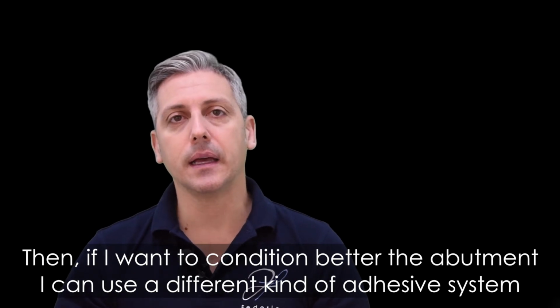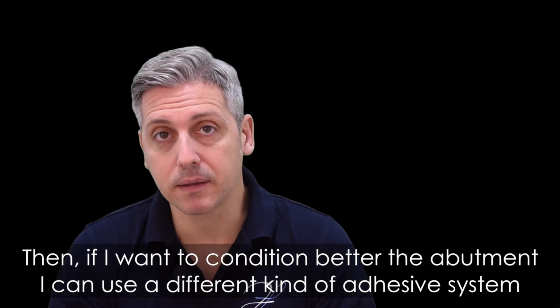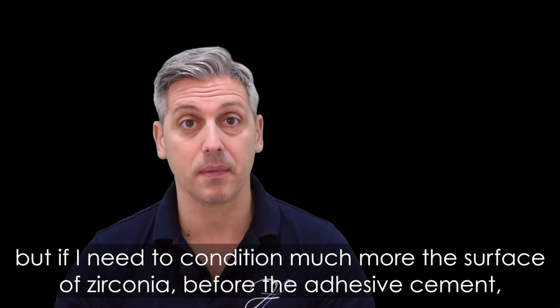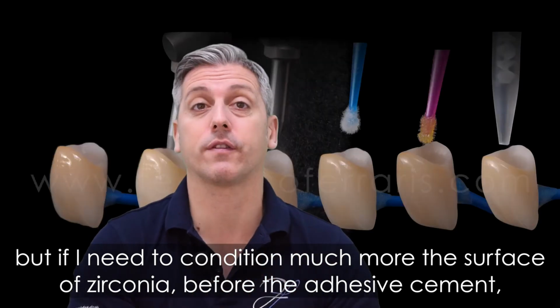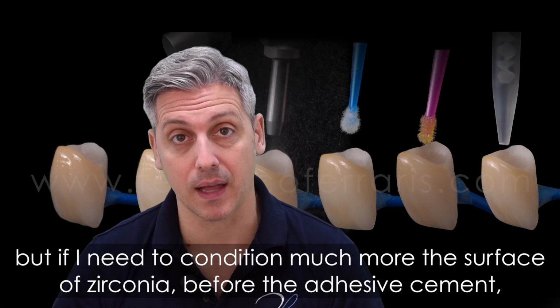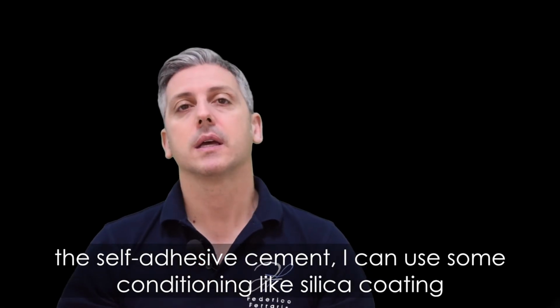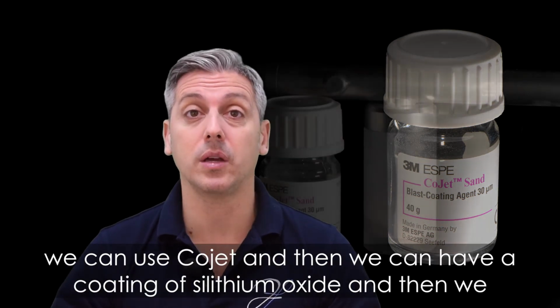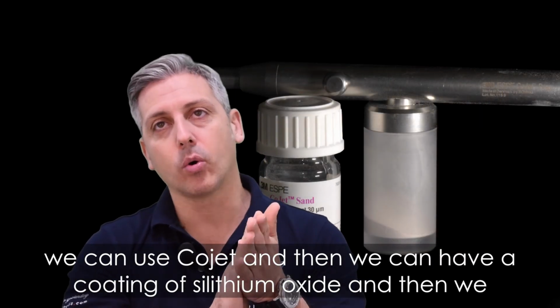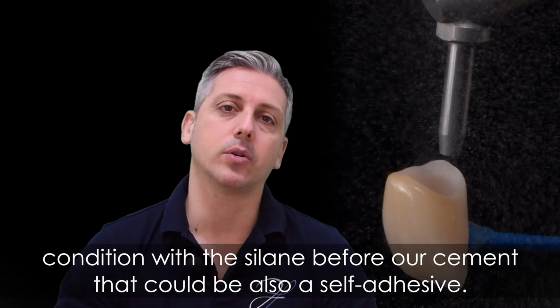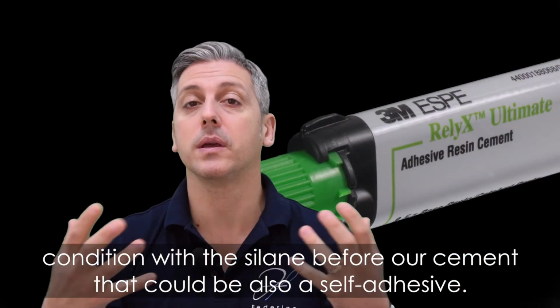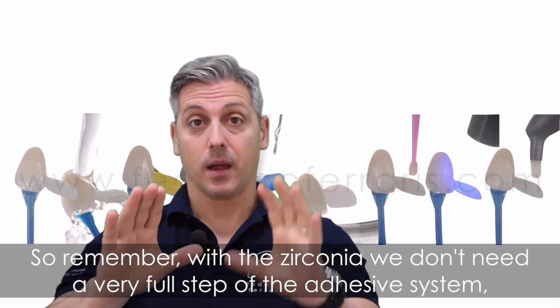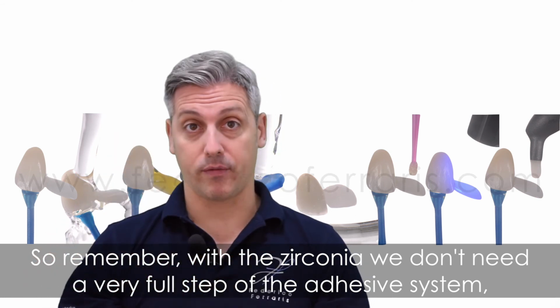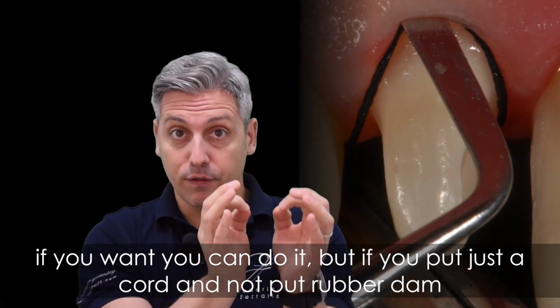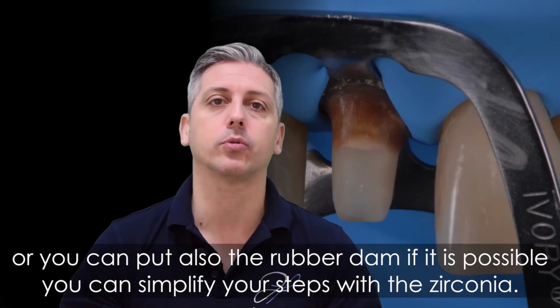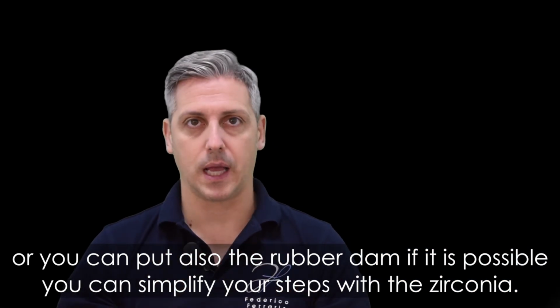Then, if I want to condition the abutment better, I can use a different kind of adhesive system. But if I need to condition the surface of zirconia much more before the self-adhesive cement, I can use some conditioning like silica coating. We can use CoJet, and then we have a coating of silicon oxide, and then we condition it with silane before our cement, which could also be a self-adhesive. So remember, with zirconia we don't need the very full steps of this system. If you want, you can do it. But if you just put a cord and not a rubber dam, or you can also put the rubber dam if it's possible, you can simplify your steps with zirconia.